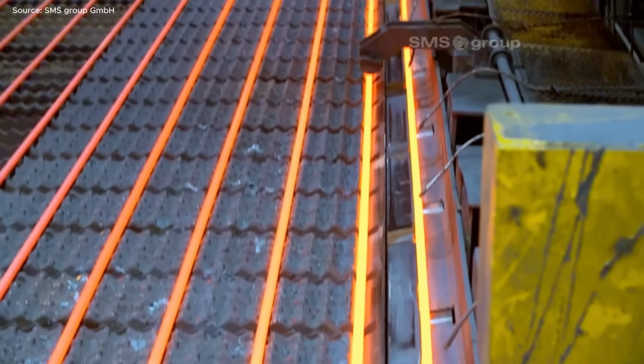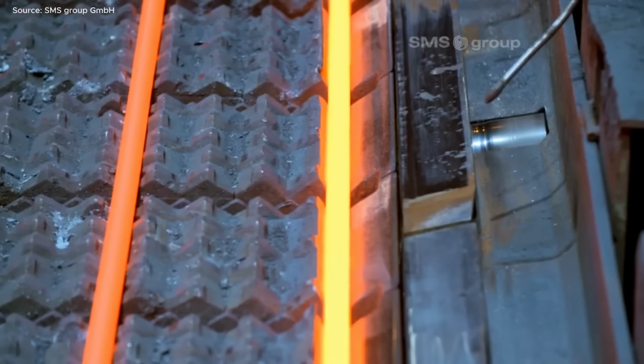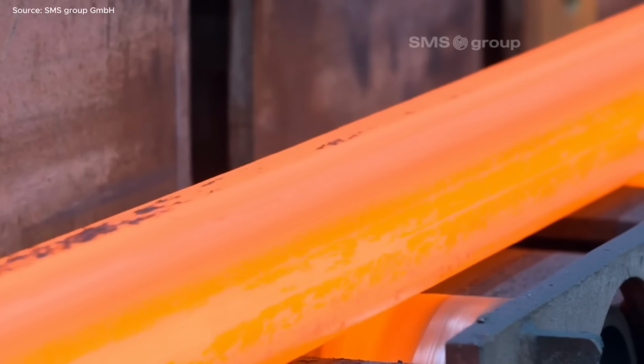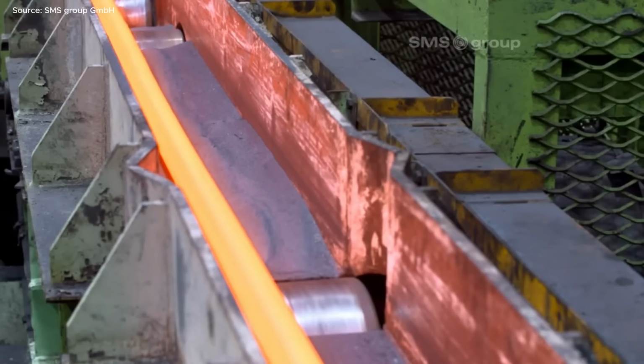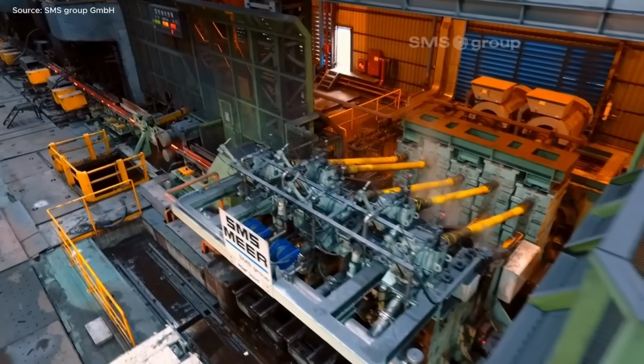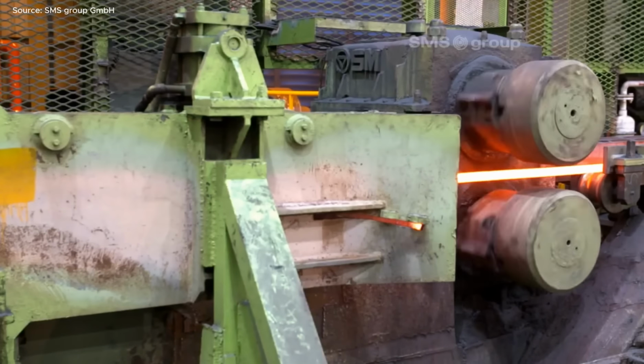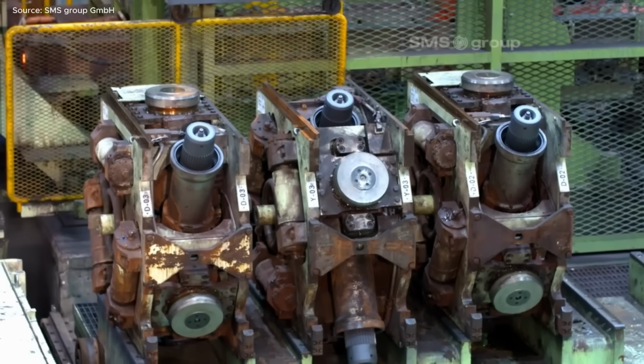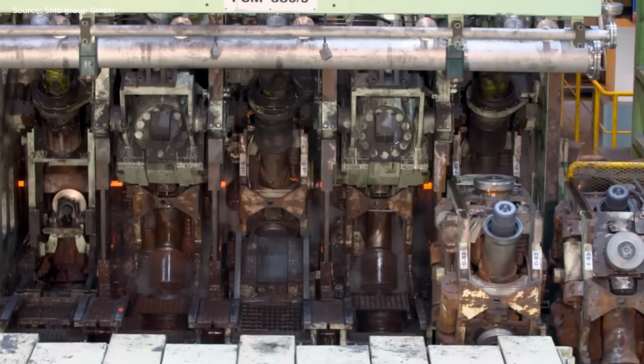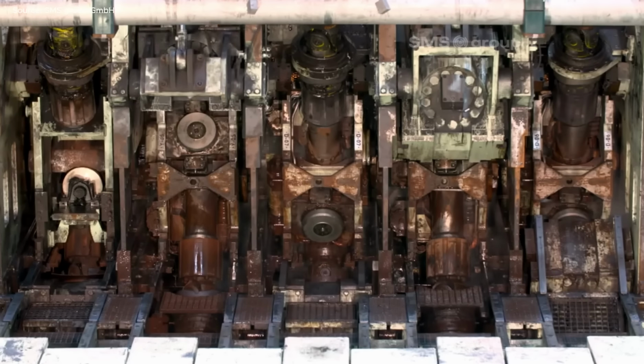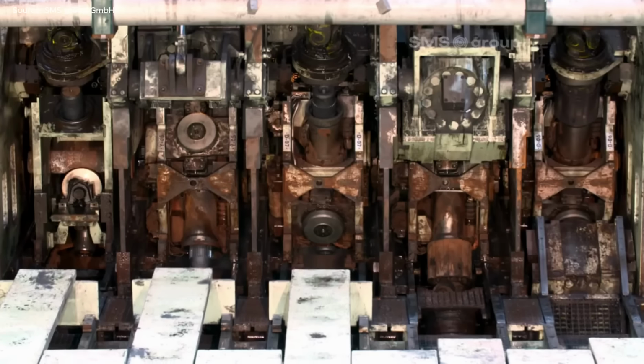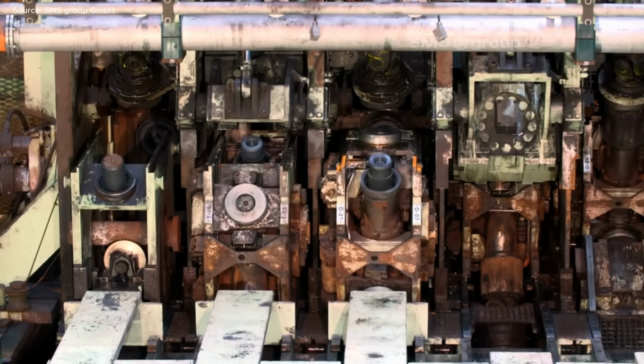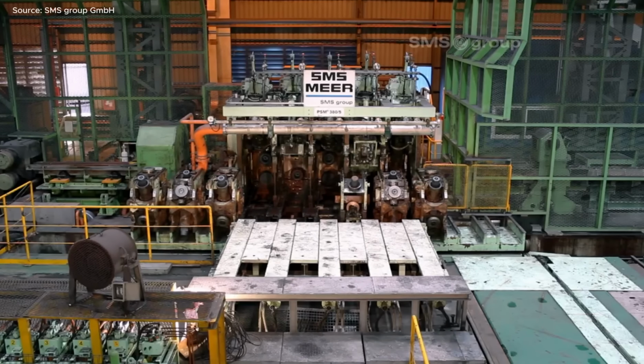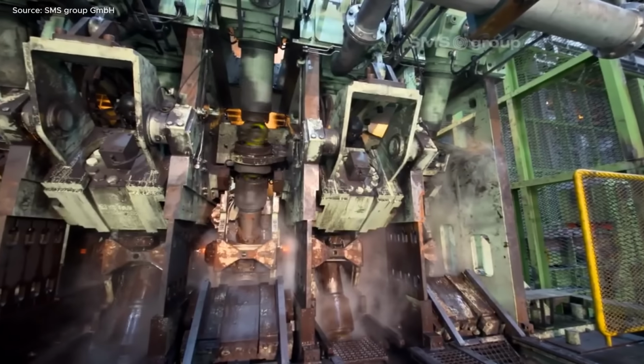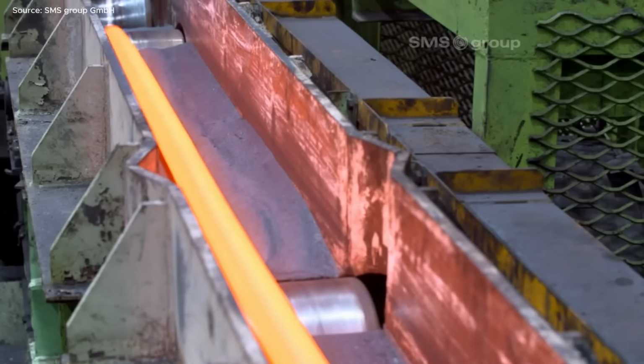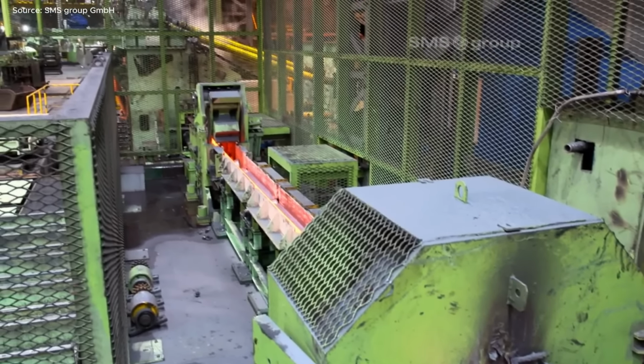A fully integrated technological control system monitors every process parameter, from roll pressure to bar temperature, ensuring consistent quality throughout production. The automatic roll change mechanism further reduces downtime, allowing rapid replacement or size adjustments without interrupting output. The result is a seamless high-speed rolling process that delivers SBQ bars from 25 to 83 millimeters in diameter, with superior surface quality, uniform microstructure, and minimal deviation.